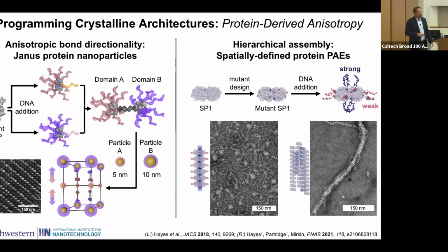We know how to do that with inorganic nanoparticles, gold particles in this particular case. And you can see this is a layered type of architecture. And I can systematically control the distance between the layers simply by controlling the central oligonucleotide here and the length of it. So it gets me greater designer capabilities. I can take proteins and I can put two different types of oligonucleotides. For example, I can put one type of oligonucleotide in the equatorial belt, labeled as a weak interactor, and a strong interactor in the axial axis here.